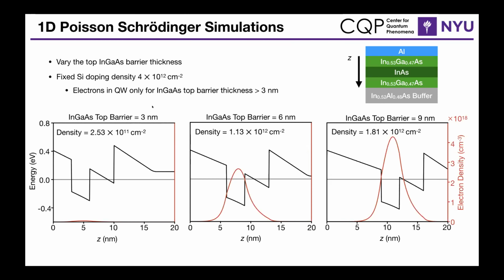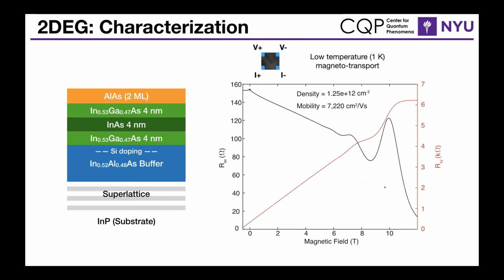And so as you can see with the fixed silicon doping density, as you increase the top InGaAs barrier, you start filling up the electrons into the conduction band, as seen in the red. So motivated by this, we grew a sample where we had a 4 nanometer InGaAs top barrier, and we introduced this 2 nanometer, or 2 monolayer, thick aluminum arsenide layer for the diffusion barrier.